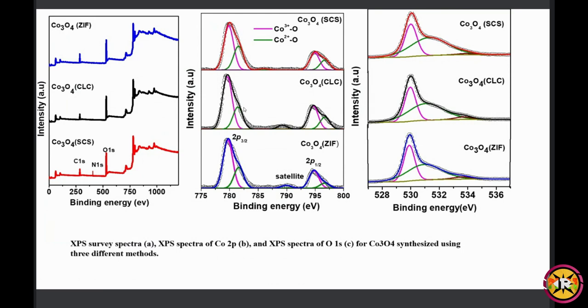The 2+ by 3+ ratio is increasing means the intensity or the area of 2+ is higher there. So when I calculated these things, I observed the cobalt 2+ by 3+ ratio in case of SCS is higher than the other two. That clearly indicates the formation of more oxygen vacancy in SCS. It is compensated with some conversion of cobalt 3+ to cobalt 2+. Now coming to figure 3.